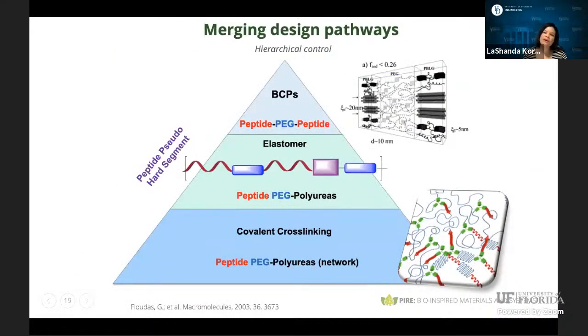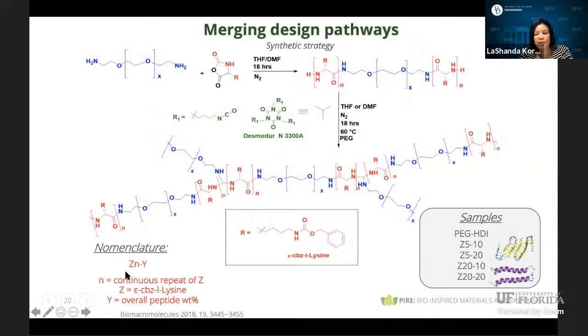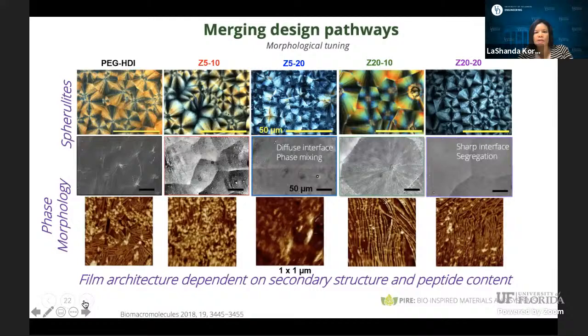Now, the last piece that I'll share with you is really about how we can build up this overall hierarchy. So we have some design rules of being able to tune these associations between the different phases. Here we can use covalent cross-linking as another handle to tune these. We use the same strategy that we used with the PBLA, but now we're using polyethylene glycol with a lysine system. We're now looking at both beta sheet and alpha helical structures, but we're limiting the overall peptide content to about 20%. That's really to drive solubility and to allow us to make some comparisons between systems. I really love this particular slide because it shows that we've been able to achieve this degree of hierarchical organization that we were so excited about.